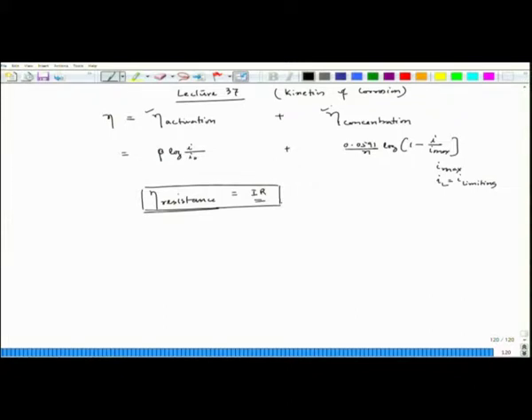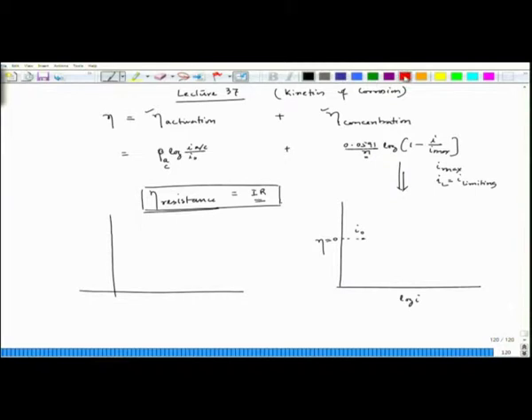Now if I try to plot these two polarizations, remember this beta log I by I0, I can write either A, which is activation, or C, where A is anodic and C is cathodic, and here also accordingly we can write A or C. I0 is nothing but the exchange current density, and here n is the number of electrons participating in that redox reaction. Now if I try to plot, the plot nature as we have seen before would be like this. This is overvoltage, this is log I, and this is the point where overvoltage is 0 corresponding to I0 of that particular metal, and if I try to plot this, this plot will look like this.